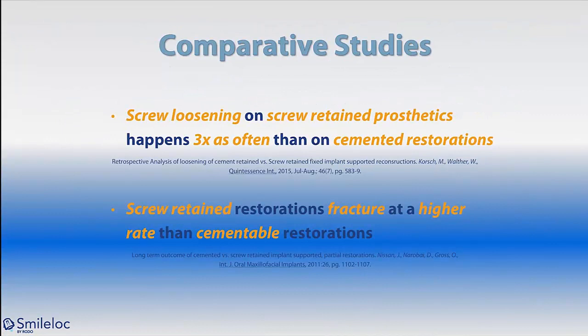What are some of the comparative studies? It was Korsch in 2015 in a Quintessence article who noticed that screw loosening on screw-retained prosthetics happens 3 times as often as on cemented restorations. Well, in actuality, this wouldn't be a bad thing because if it's screw-retained and it gets loose, we could always retighten it. If this happened more on the cemented crowns, it would be a big problem. Also, screw-retained restorations fracture at a higher rate than cementable restorations. And Nissen, back in 2011, did a retrospective study and came up with that knowledge.